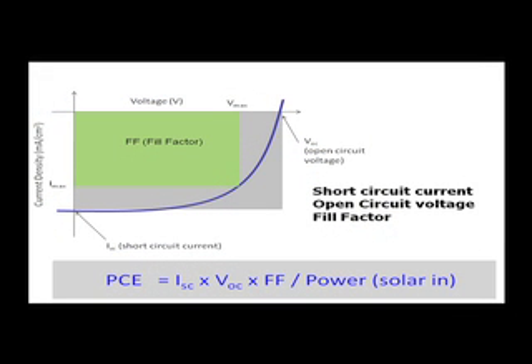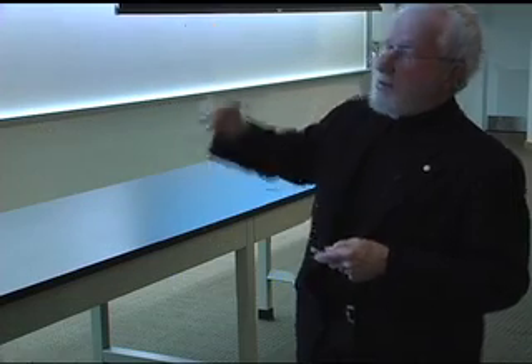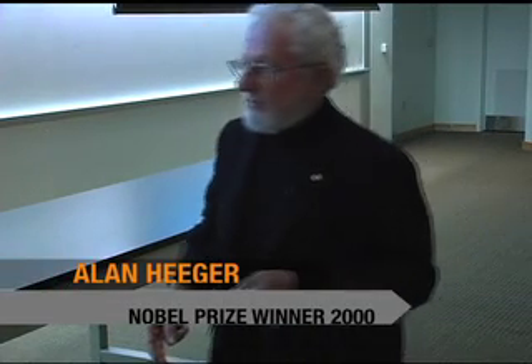But the essential point is that I would like to always try to make my donor and my acceptor such that the energy gap of the donor will be fairly small, so I can absorb the full solar spectrum, which goes all the way out into the infrared. And we know that silicon does that very well. So I'd like a spectrum which is in fact close to that of silicon. And I'd like to make this energy as close as possible to this one. So I'd like to bring these together with an offset that is just sufficient to enable the charge transfer.